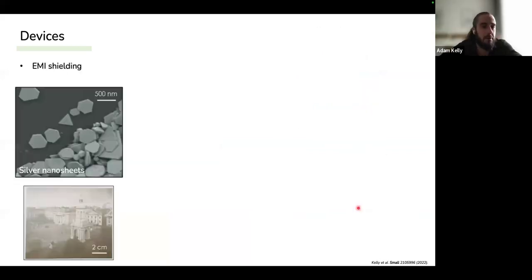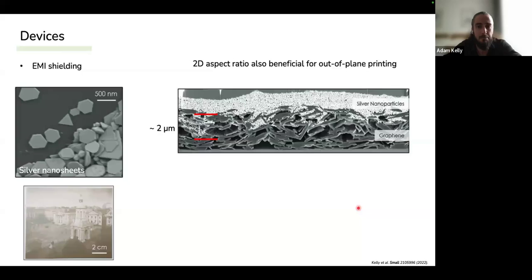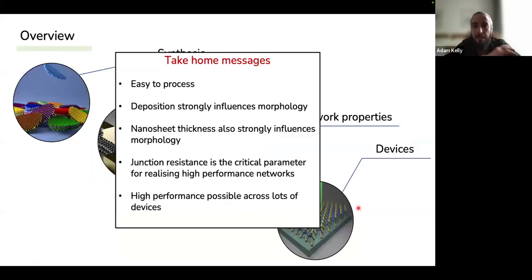So I do have some stuff here on EMI shielding, but just for the sake of brevity, I will leave it there. And I will say the take-home messages from all of this are these materials are easy to process. The deposition method itself strongly influences the morphology. The nanosheet thickness itself is a very important factor, and this influences morphology too. You really, really need to care about your junction resistance if you want to get high performance networks. And high performance is then possible across a range of devices.